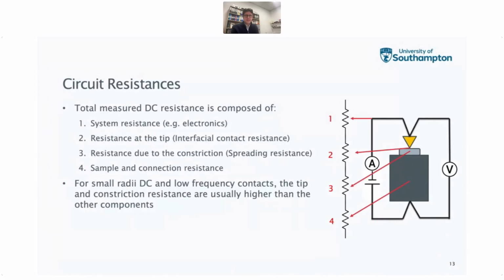Now, if you do this, you need to take account of some of the resistances that you're measuring in this technique. And usually they're comprised of 4 main resistances that we need to consider. So there's the system resistance, which is the electronics and the resistance that that might provide. There's the resistance at the tip when you actually make contact between the sample and the tip, and we'll call that the interfacial contact resistance. There's the resistance due to the constriction as you penetrate. So that's known as the spreading resistance, as the resistance as the current goes off into the two materials. And then there's the resistance of the rest of the sample, the connections, and back to complete the circuit.